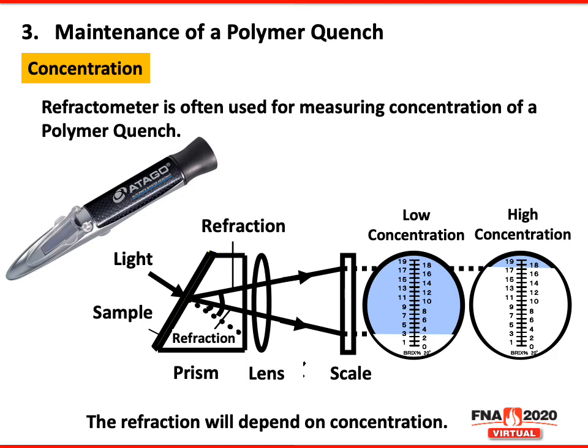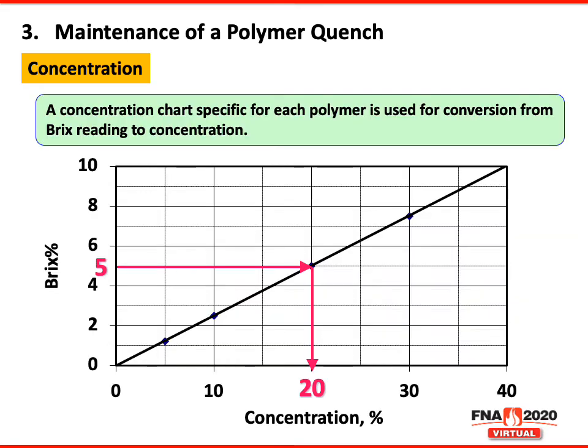So how do you take a concentration sump side? You use a handheld refractometer, and the refraction, which means bending of the light, will depend upon the concentration. A high concentration will give you a higher number, low concentration gives you a low number. You take that number over to a chart, and the chart varies for every polymer. And you take your brix percent, draw a straight line over to your curve that you have there, and then look down, and you can determine your concentration.